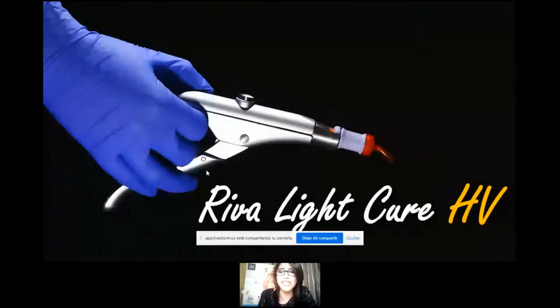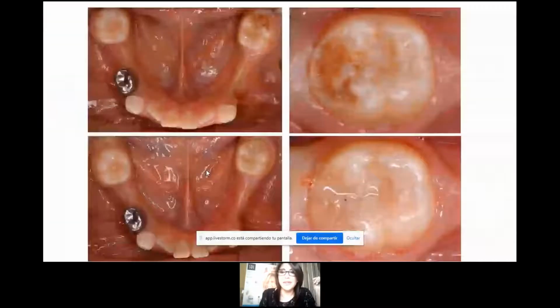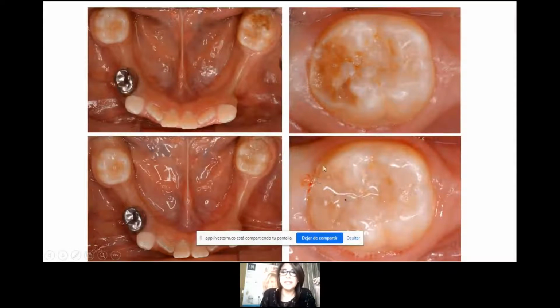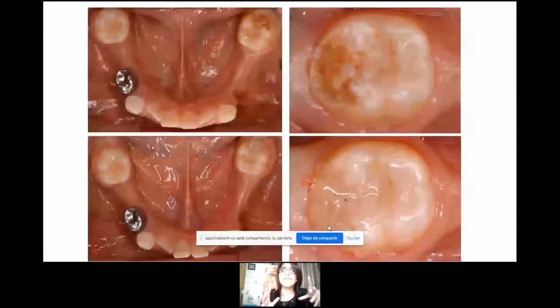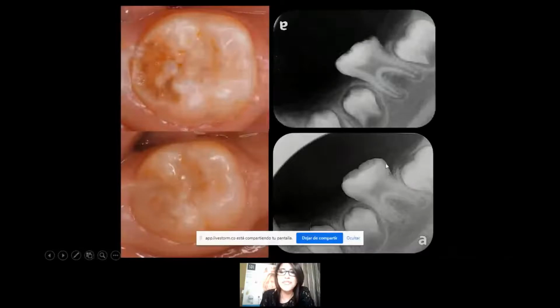And in hypomineralization, when you have it not only in enamel but the cavity is in dentin, I prefer to use Riva Light Cure High Viscosity. For example, in this case, look here, I used the Riva Light Cure High Viscosity here because I will have both. I will have the strontium, okay, for bioremineralization and remineralization, and the resin and the high viscosity will give me resistance to the occlusion forces. So it's great, this material. Look here, how is the sealing, perfect, okay? You look, perfect, the bioremineralization and the remineralization.